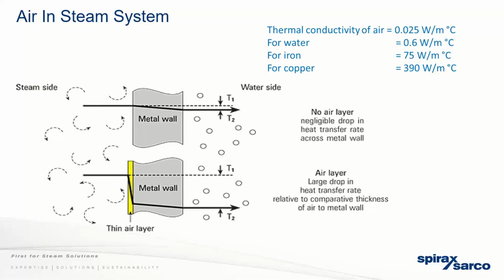So that's one of the other reasons why you would want to deaerate, because deaeration not only removes oxygen, it's also getting rid of air, to an extent. A chemical oxygen scavenger is only reacting with oxygen. It's not doing anything else with any of the other gases. And even with oxygen corrosion, you could get pitting. You could also get carbonic acid formed on the condensate side.